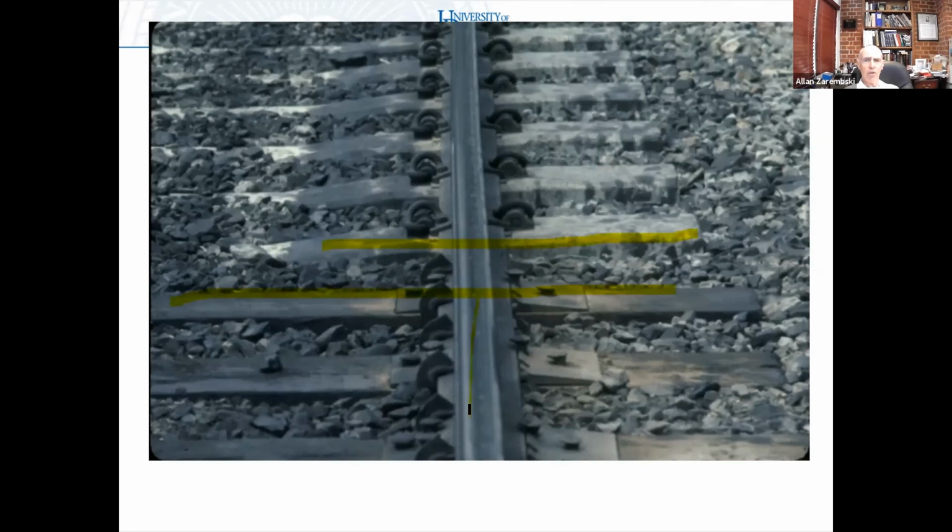You notice there's a very nominal amount of corrugation here, and there's a much more dramatic amount of corrugation here. And we see this all the time. We see this in metros, where you go from a slab track to a ballasted track. If you have a transition from ballasted track to slab track in a metro, we very frequently see corrugations develop at that stiffness transition. So the theory is that that difference in dynamic response when you get to a stiffness transition causes that more rapid development of corrugation. And we know we see more rapid corrugations on stiffer track than we do on softer track.